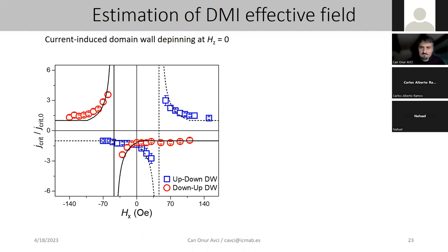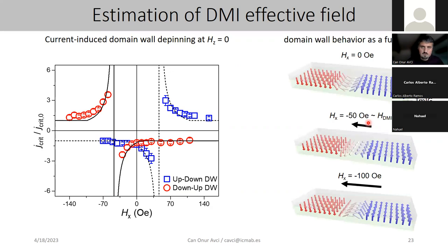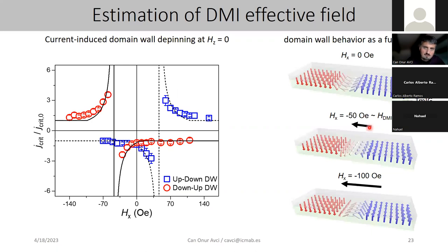So imagine that now at zero field, you have a fully Néel type domain wall. If you apply a minus 50 Oe field, then you cancel this effective DMI field and you get a Bloch type domain wall. And then if you increase the in-plane field, you make a Néel type domain wall with the opposite chirality. Therefore, you need the opposite polarity of current to drive the same domain wall, as you can see here. So for a larger negative field you need positive current, and for zero field or positive field, you need a negative current in the case of the down-up domain wall, and the same for the other, up-down domain wall.